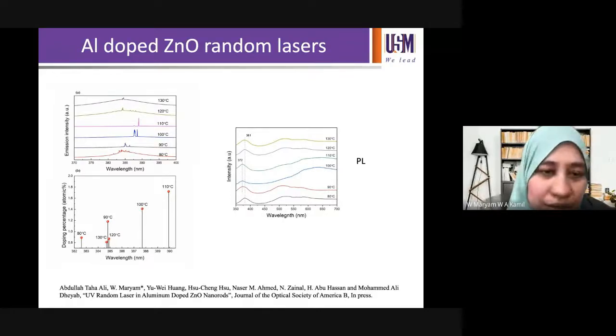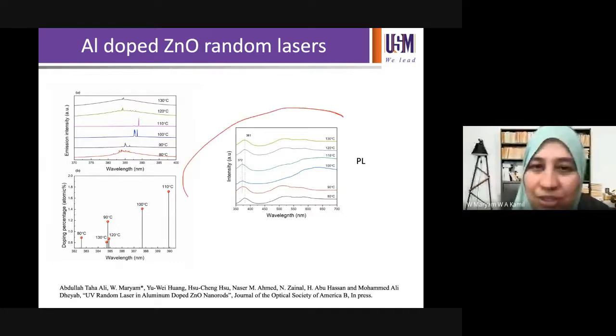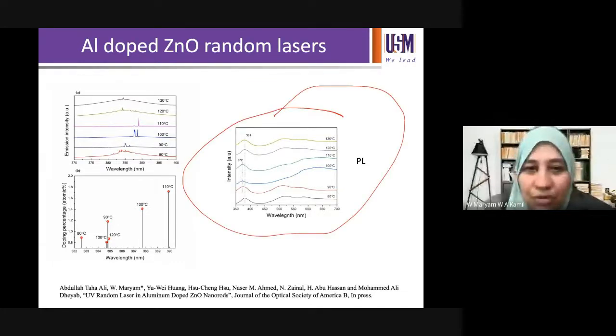So basically, the random lasing shifts in terms of wavelength as we increase doping. Okay, so this is increasing our doping percentage, and then we see that the wavelength of the random laser actually shifts. Okay, and we notice that this shift is actually related to the photoluminescence that you see here. If you see here, there is a shift of this green peak going to here